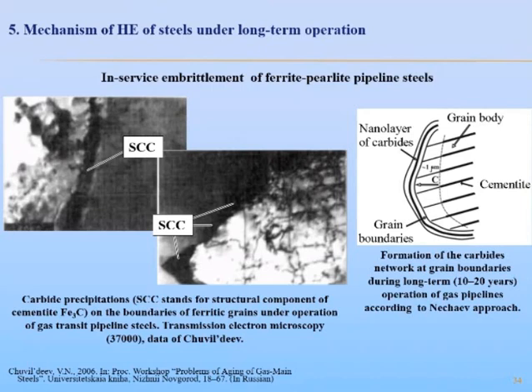Changes in microstructure of long-operated pipeline steels of gas transit pipelines observed experimentally as precipitation of carbides at the grain boundaries, as it was reported by Chivildeev, and presence of carbides at grain boundaries affects stress corrosion cracking resistance of pipeline steels under operation. And it was suggested by Nechayev that during a long-term operation of steels, carbide-like and other nanosegregated structures are formed at grain boundaries.